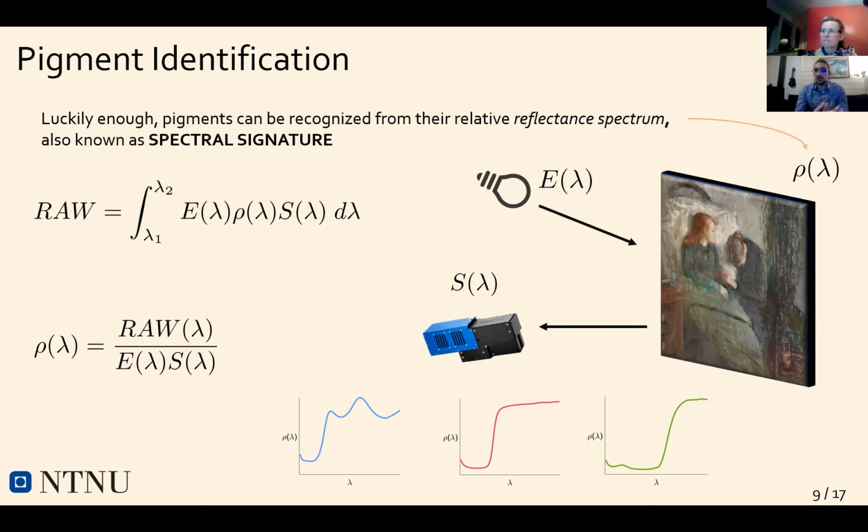And if we know how cadmium yellow looks with the reflectance, we can look through the painting and see with some specific metrics if there are spectra that are close or matching to the spectrum we are looking for. But then, of course, we will not be 100% sure. We will be maybe 80% sure that that pigment is present in that pixel of the image.